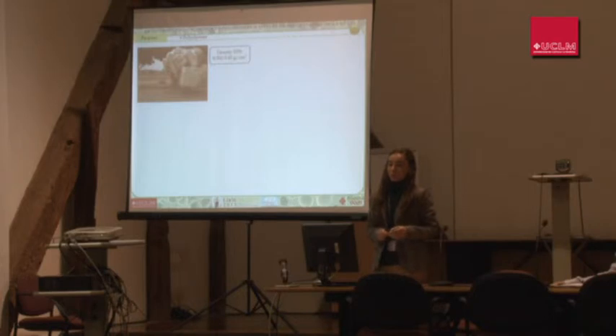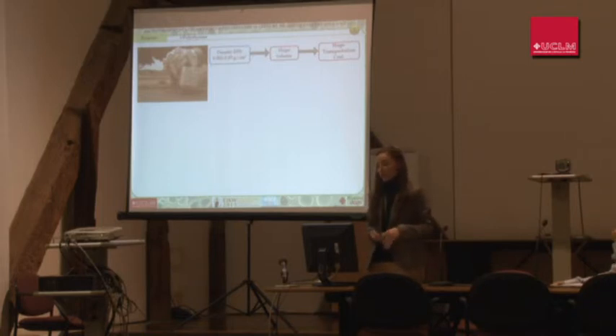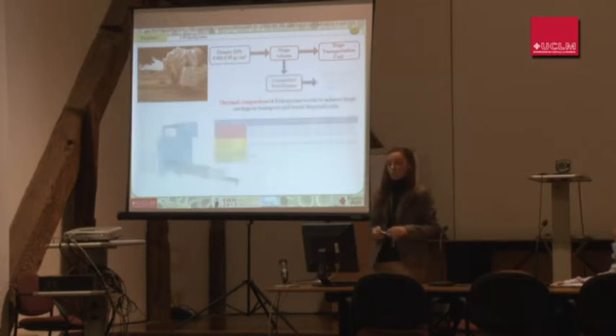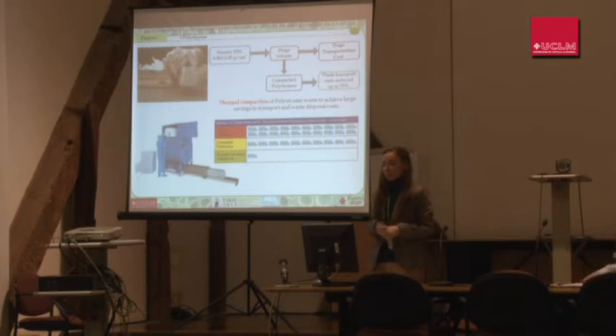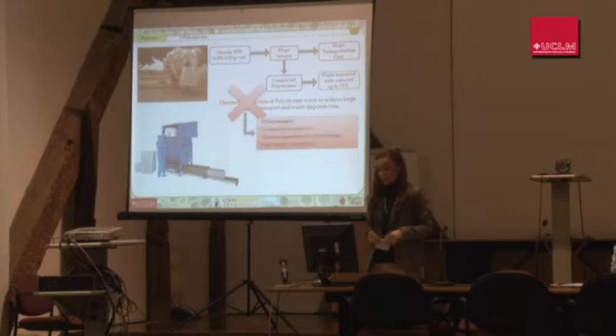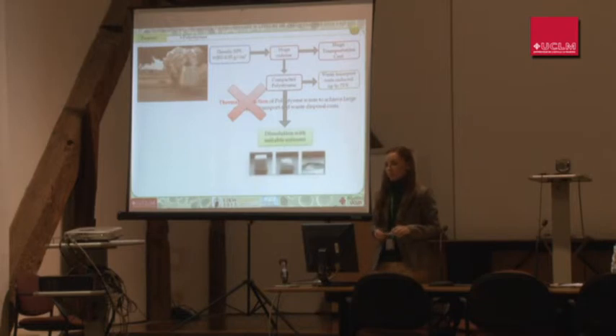The main problem present in polystyrene waste is its low density, which is responsible for a huge volume of waste that should be transported, and consequently there are important costs associated. For this reason, it was thought to reduce its volume by means of compaction, but the problem is that during this thermal process there is an important generation of undesirable byproducts as a consequence of the thermal degradation of the polymer chains. To overcome this problem, we propose the use of suitable solvents that can achieve a volume reduction without degradation of the polymer chains.